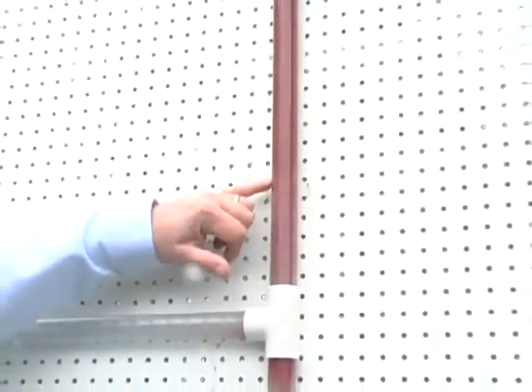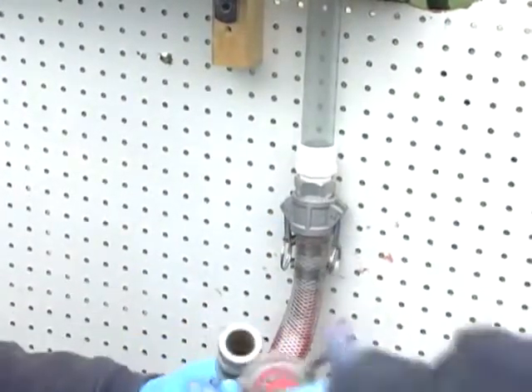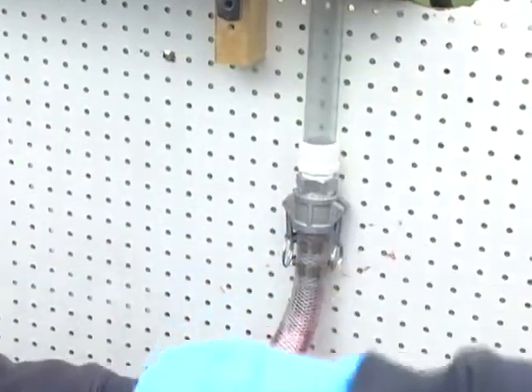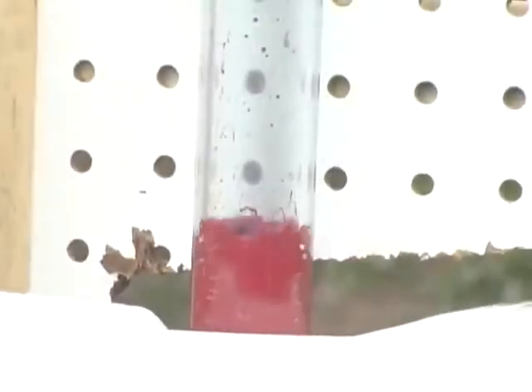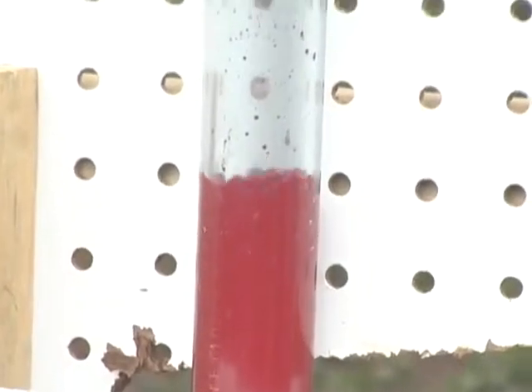Although only 10 to 12 mils thick, the coating completely repairs most corrosion, pinhole, or other leaks, while creating a permanent seal between the water and any of the contaminants that can be found in older pipes. By controlling the airflow, our technicians can push the coating away from gravitational pulls and around 90-degree bends while choosing the direction of flow at each joint.